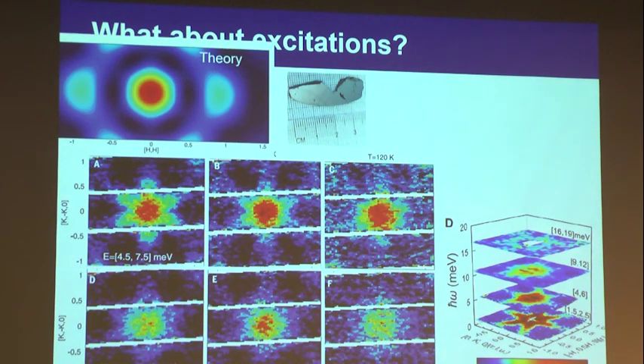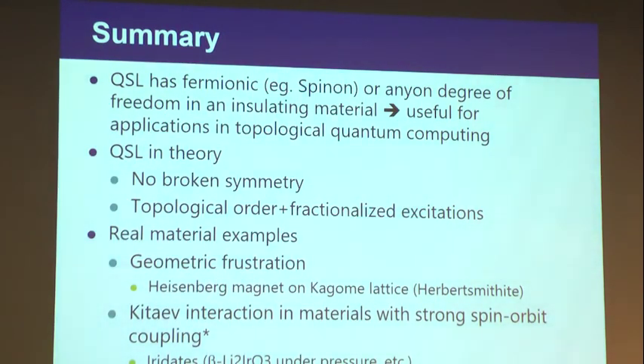And you can compare your result with a theoretical calculation that assumes that the Kitaev interaction is quite sizable in this system, or when you have a Kitaev type of ground state, then maybe it's similar. So there's a faint lobe that's pointing in all these six directions. Maybe it's similar, maybe not. So again, this is a very rapidly developing field, and I'll probably have more of a story to tell you in a few years. Okay, so that's about it in terms of this.